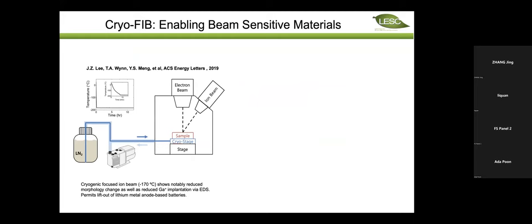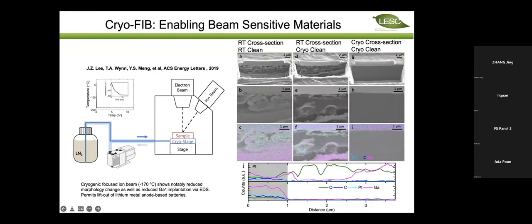Okay, so lithium metal is not an easy material to study because it's so sensitive to everything. If you look at the ABC first column, this type of SEM picture was everywhere in the literature before 2019, I would say. When you use the gallium ion beam to cut the lithium metal, you actually get severe contamination from the gallium beam, because the gallium was actually alloying with lithium at room temperature. We showed that you really need to use both cryo cutting and cryo cleaning if you want to study vapor deposited lithium metal carefully. So this is a sheet of lithium metal that is supposed to be a dense metallic phase, but if we don't have the proper tools, the lithium metal basically reacts with the gallium ions.